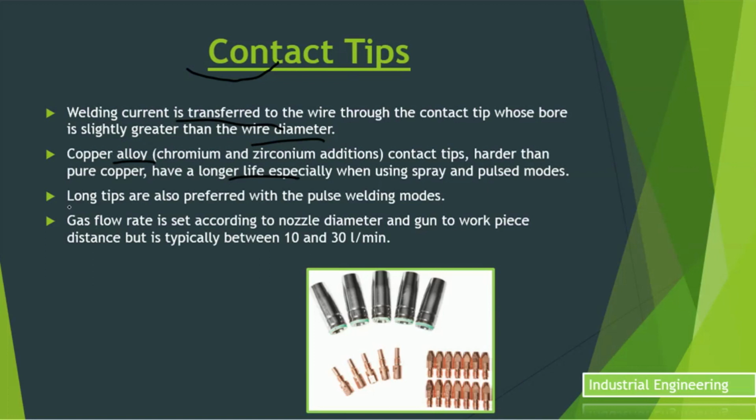Third point is long tips are also preferred with the pulse welding modes. Gas flow rate is set according to the nozzle diameter and gun to the workpiece distance, but is typically between 10 and 30 liter per minute.